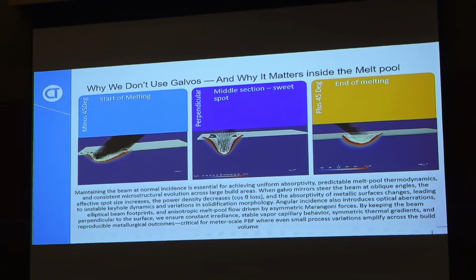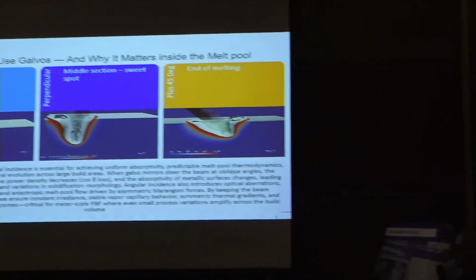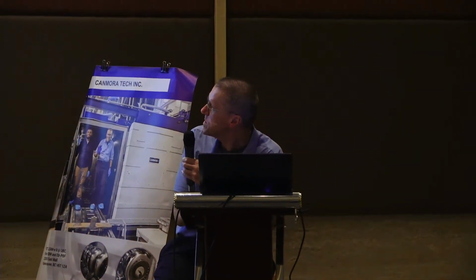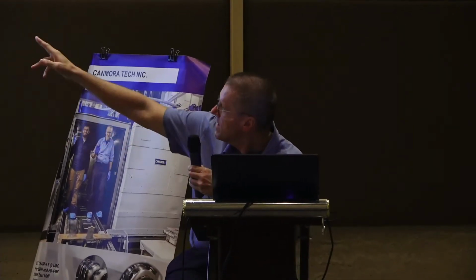The second problem we found is when you angle the beam, there is a lot more porosity. So you will see that there are these little bubbles in this, let me see, here. You see these bubbles here. These are actually defects, okay? These are literally little gas bubbles that are created in the melt pool. And then you can see that, especially in the beginning, there is a lot. Here are some. That's how the flow of the metal is going into the melt pool. And in the vertical condition, you still have them, but less so.